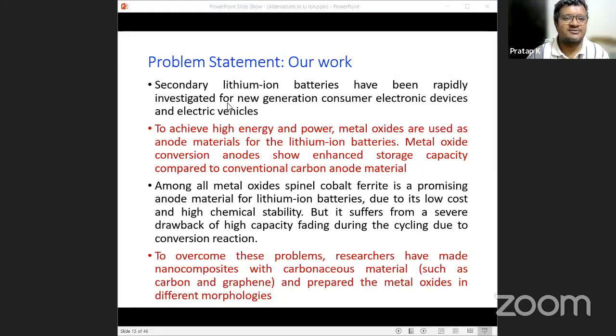So what we try to do in our lithium-ion batteries is, we try to check secondary lithium-ion batteries that have been investigated, and to achieve higher energy density and power, metal oxides are used as anode materials, and metal oxide conversion anodes should enhance storage capacity. So we have chosen metal oxides, but which type of metal oxides are good? So we have chosen spinel cobalt ferrite as an anode material, and it has a severe drawback from capacity fading.